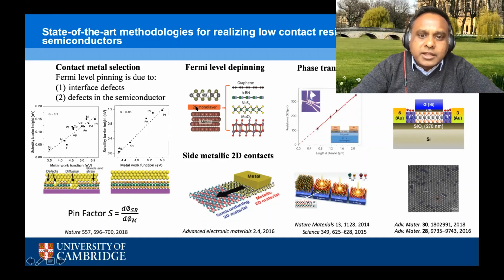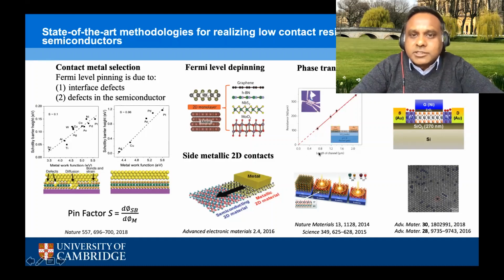For example, side metallic contacts, or placing something like hexagonal boron nitride between the metal and the 2D semiconductor, so that the hexagonal boron nitride acts as a tunnel barrier, and the metal atoms are prevented from causing damage during deposition. A few years ago, we also showed that one can use the metallic phases of the 2D semiconductors to achieve very good contacts. That was followed up by Young-Hee Lee's group, showing similar results. One can also do doping. This is, I think, some work done by Ali Javey's group, where they used local doping similar to what one would do in silicon devices to make good contacts. And as I said, doping of foreign atoms into 2D semiconductors is always a little bit problematic because of the high probability of causing damage.